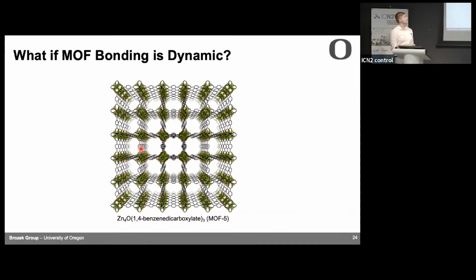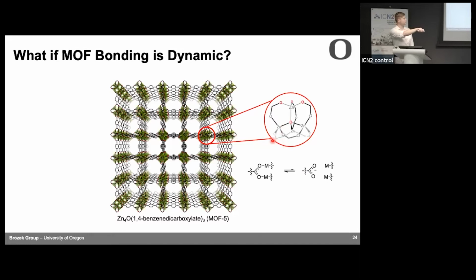It's not flexible. But in the last 10 or 15 years or so, we're now knowing that this isn't really the case, and they're much more interesting than just these static structures. And so if you focus on, this is MOF5, if you focus on the MOF5 cluster, and you look at those metal carboxylate bonds, we know that molecular versions of these metal carboxylate bonds are really dynamic, at least for molecules. They're always in an equilibrium between being bound and unbound. So that had us thinking, what if this is true for MOFs as well? And that would be very different from this idea that a MOF structure is just this fixed, rigid thing that you see in the picture.